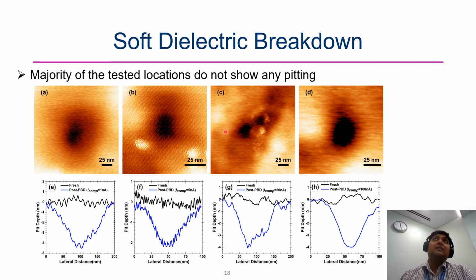What we found is that when we do these experiments under, for example, UHV conditions and under soft breakdown conditions, the majority of the hBN tested sites do not show any pitting. We do not see any pitting in the soft breakdown conditions. What I am showing here are some of the results where we do see some pitting. Only for some locations there are pits, and the size of the pit also depends on the current compliance that we use. In our case, when we limit the current compliance to 100 nanoamps, we saw a pit of 3 to 4 nanometers formed. This is a partial pitting.